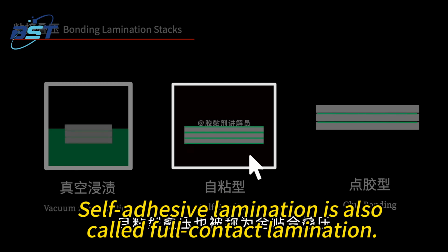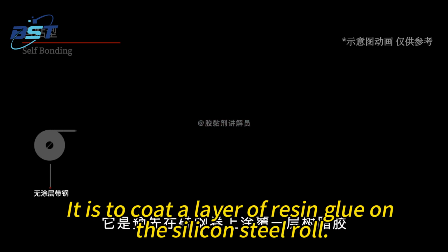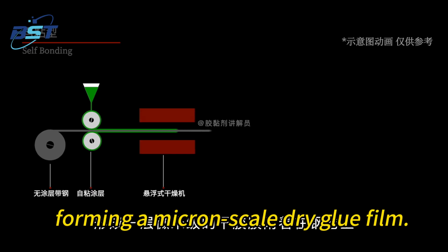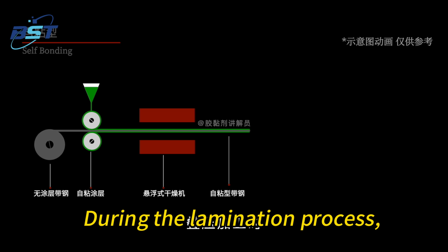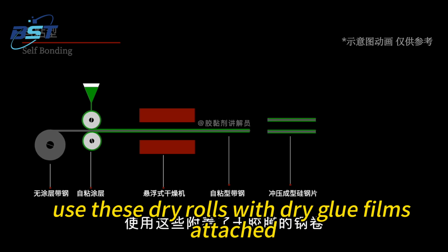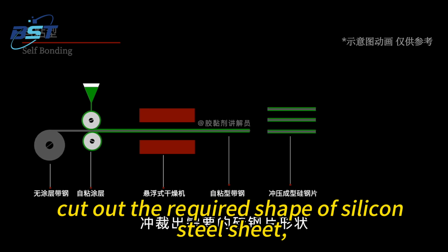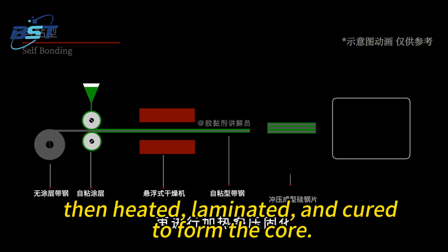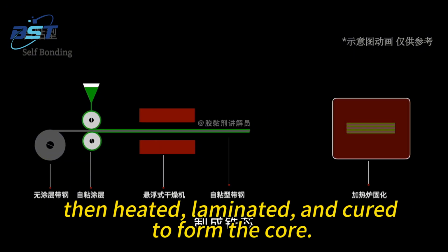Self-adhesive lamination is also called full contact lamination. It is to coat a layer of resin glue on the silicon steel roll. After baking and drying, a micron-scale dry glue film is formed, attached to the roll. During the lamination process, use these rolls with dry glue films attached, cut out the required shape of silicon steel sheet, then heat, laminate, and cure to form the core.